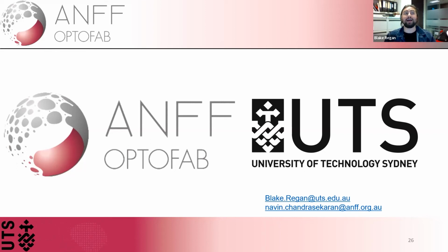which then has a higher probability of introducing single photon emitters. However, if you're actually aiming to get single photon emitters, I recommend, depending on your application, working with nanodiamonds, where you can delta dope them a lot more appropriately because you'll have a much smaller volume to work with, or ion implantation, which I believe is a capability that our ANU hub might have. I know that's where I've sent things. I'm just not sure whether that's associated with ANFF.